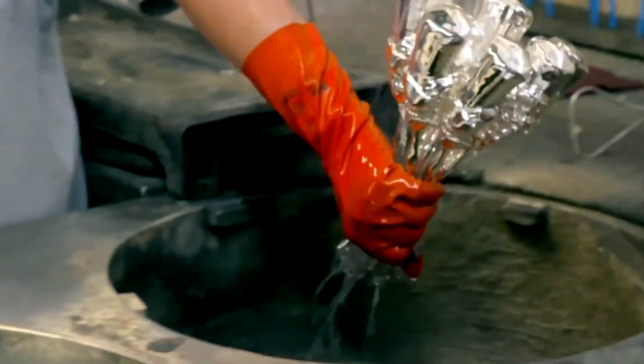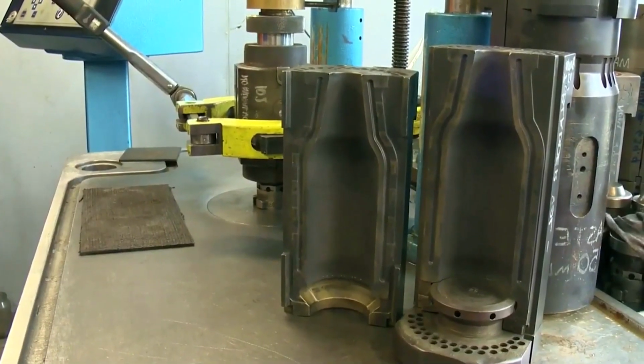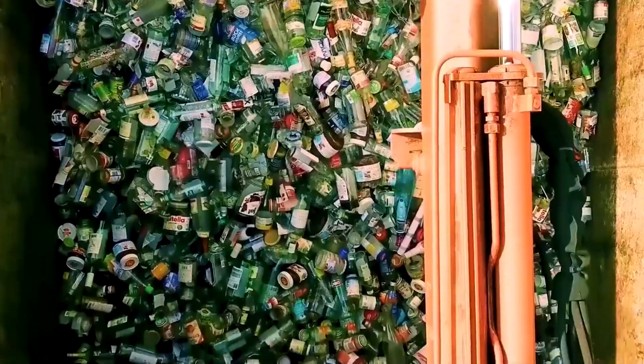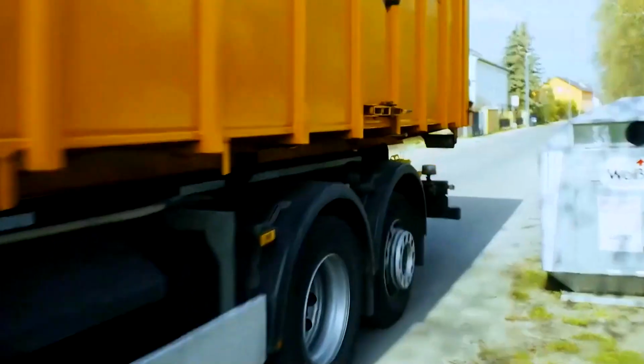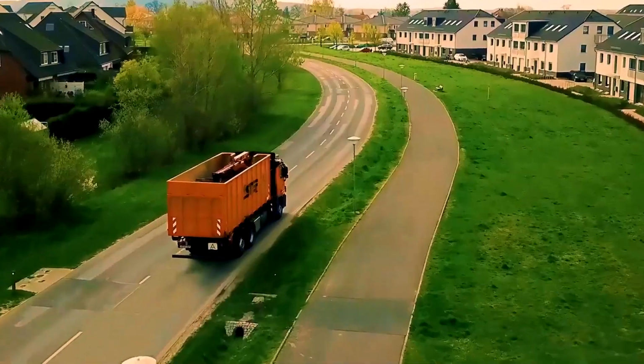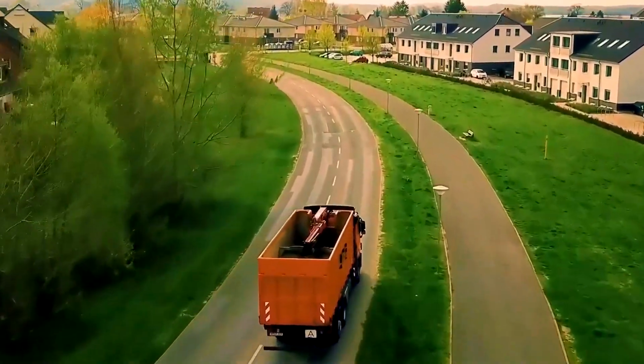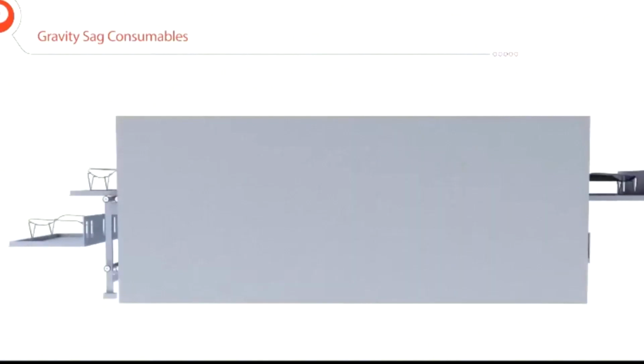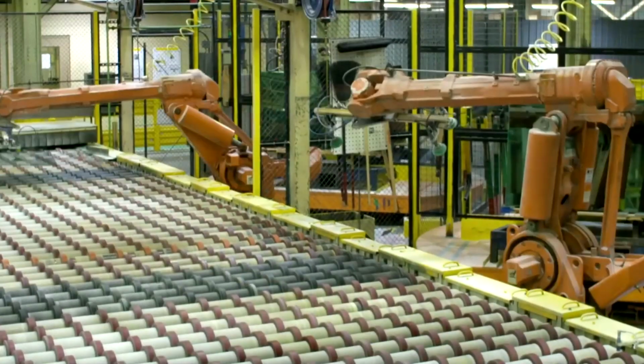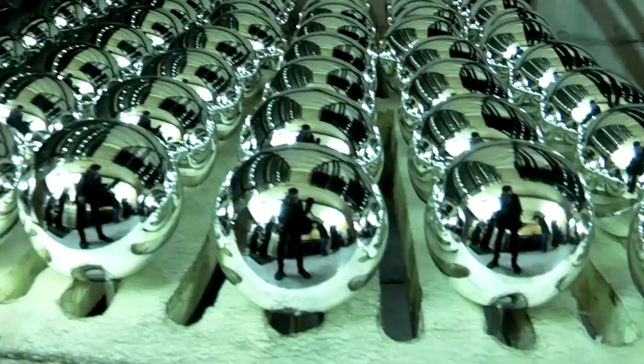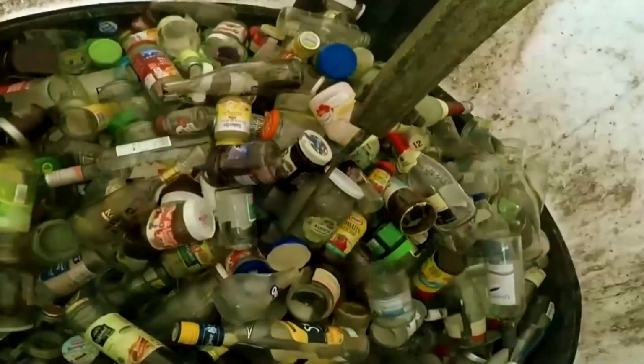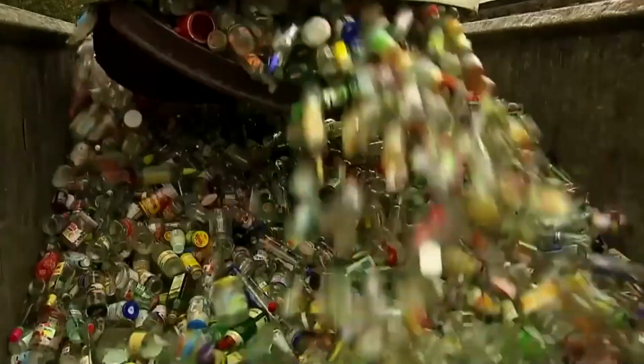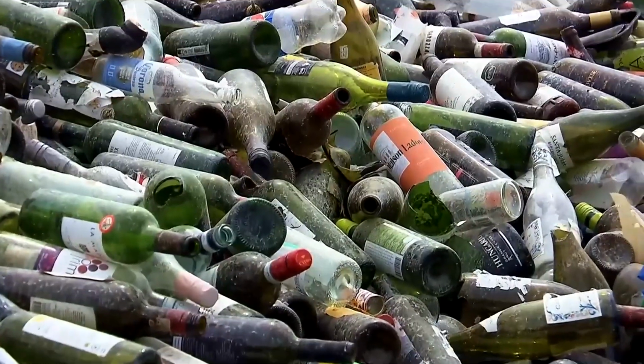The process initiates by releasing drops of molten glass, known as gobs, cut from a continuous stream at temperatures reaching 1,100 degrees Celsius. Gravity pulls the gob into the preliminary mold, where a jet of compressed air forces the material outward against the walls. This creates a parison, a hollow bubble with a narrow neck, which is then transferred to the final mold. Here, a second burst of air stretches the soft glass until it hugs every detail of the metal cavity. In mere seconds, the full shape of the bottle is born.